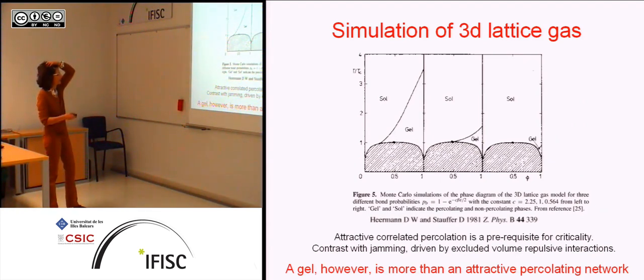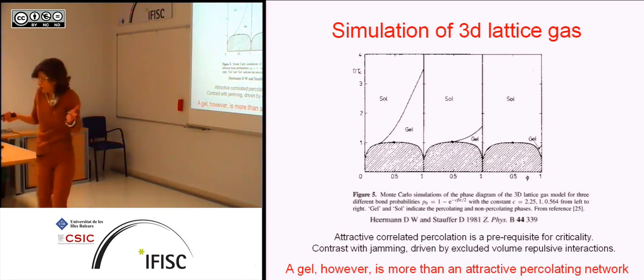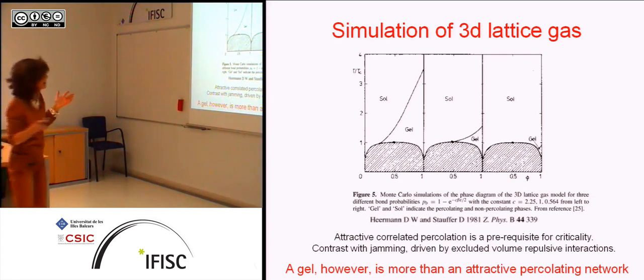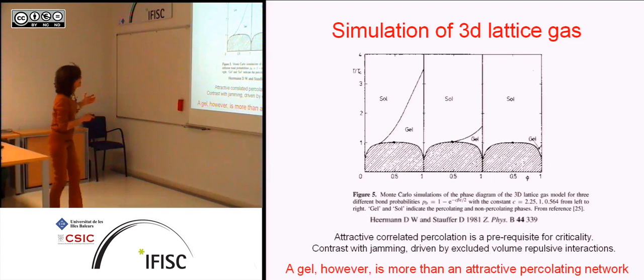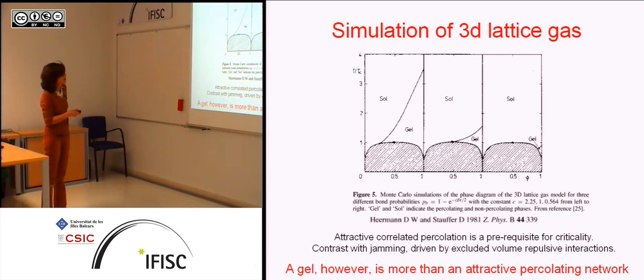Okay, the simulations of an Ising model, this time a 3D Ising model. So this is just a phase coexistence of the Ising model, and defining the probability of bonding. This is a bond correlated model, so this is an Ising model, and then I define these clusters by defining a bonding probability, which I can write any way I like, basically, if it makes sense. And this is basically what this is. Dieter Hermann and Dietrich Stauffer again in the 80s, they saw that these clusters do coincide with the Ising clusters for a particular choice of this bonding probability.